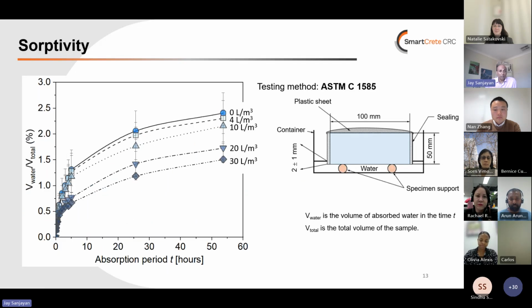We also did some work on sorptivity, and you can see the absorption period up to 56 days, I think we did. And when we add paint, the water absorption into the concrete decreases. That's what you can see from this slide.